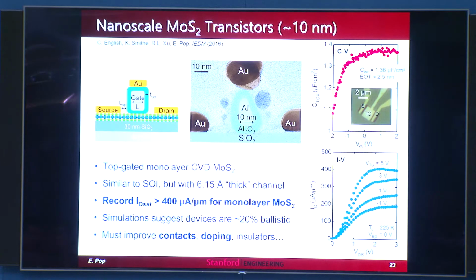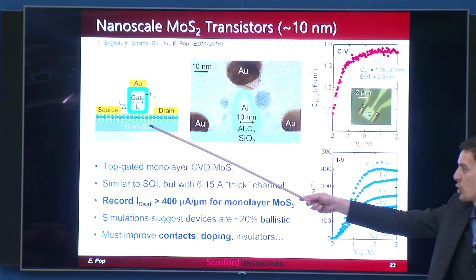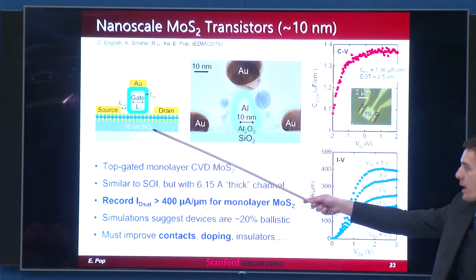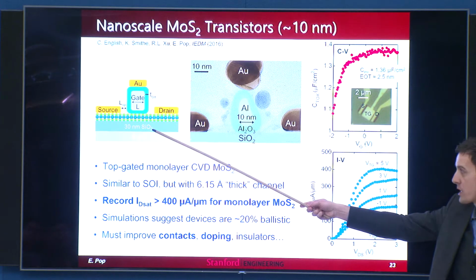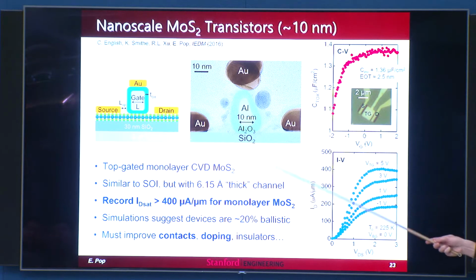On a related note, if you have a motivated student and a decent E-beam system, you can take these materials and actually make them into 10 nanometer gate transistors. This, by the way, is a cartoon, obviously. This is the real finished device. What I like about this is it looks like an SOI device, if you're familiar with SOI devices, but it's really made with a 3-atom thick channel, right? So it's kind of like the ultimate SOI device in a certain way. At the time, the saturation current in these devices was about 400 microamps per micron, which is reasonable. If you look at SOI papers, they do a little bit better sometimes, but it's done with much, much thicker silicon, at least 10 times thicker.